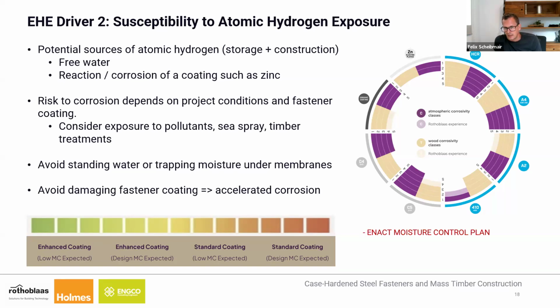We can do things like avoid standing water, but again, particularly important for things like your steel plate connections that are put on your CLT floors, where oftentimes the water has nowhere else to go. So unless it's correctly covered, and I say correctly covered because it's not just covered by a plastic membrane, it has to be something that's highly breathable that lets the moisture out. But the water will sit under the steel plates, and it's very clear from testing that we've seen out on the building sites that around it might be completely dry.